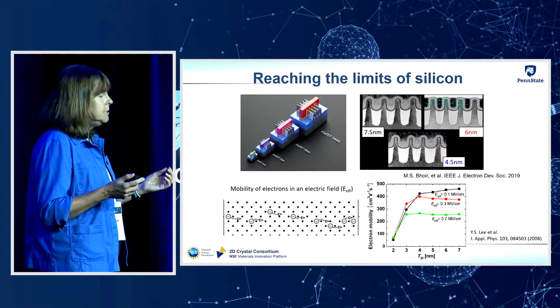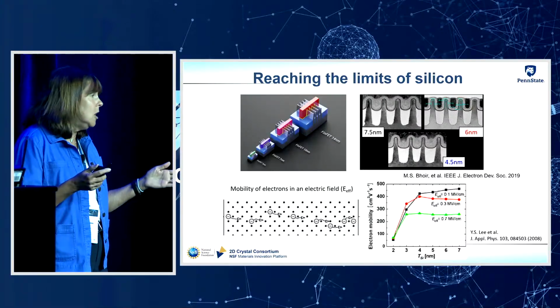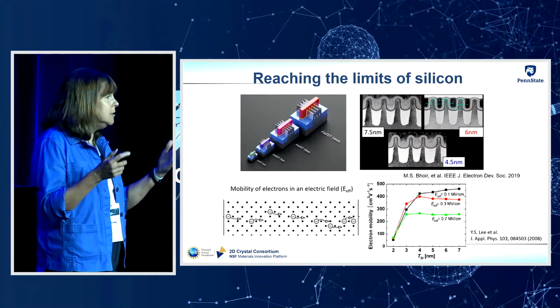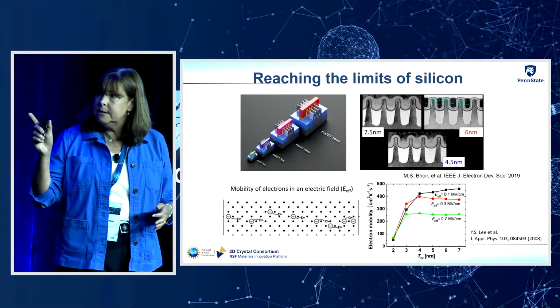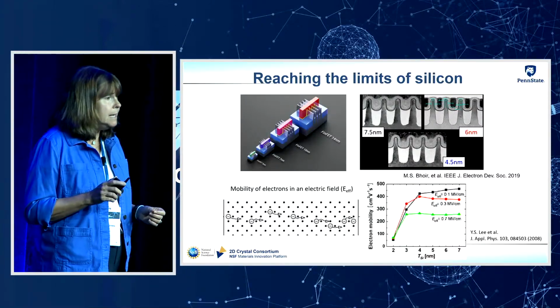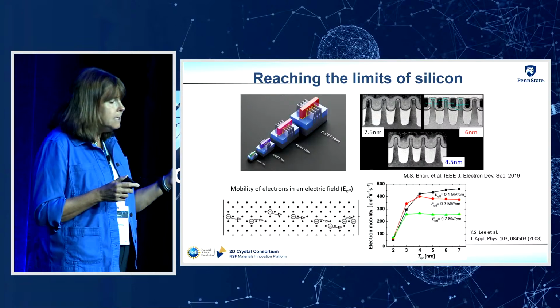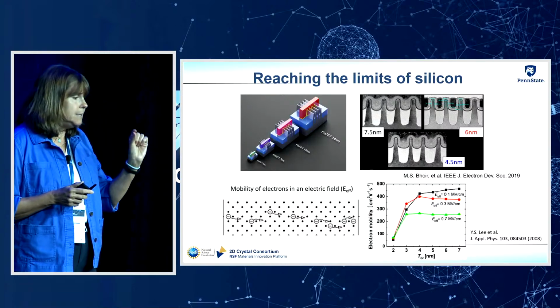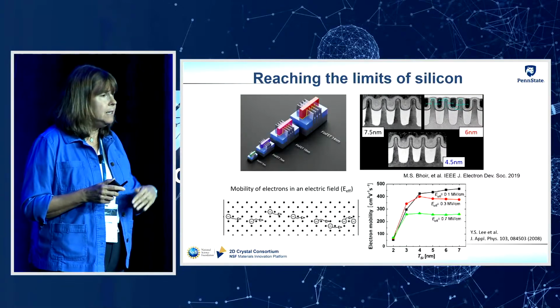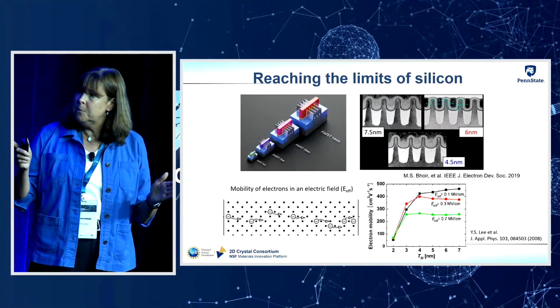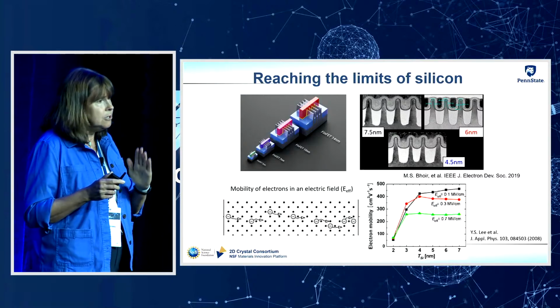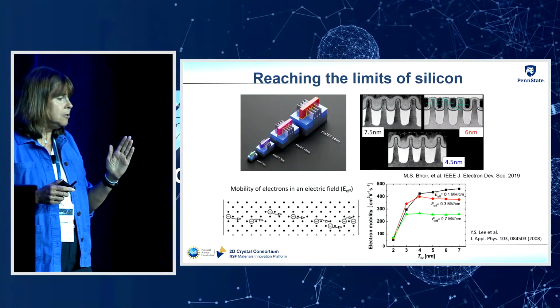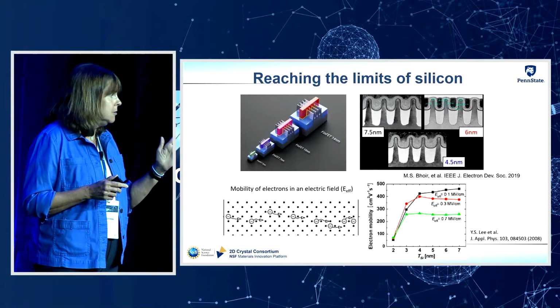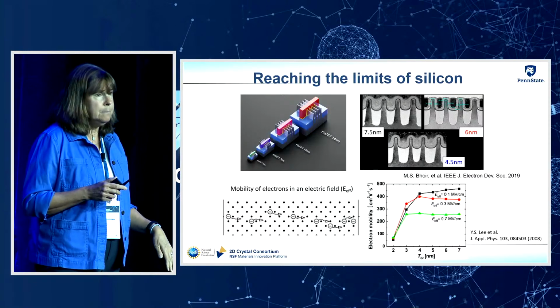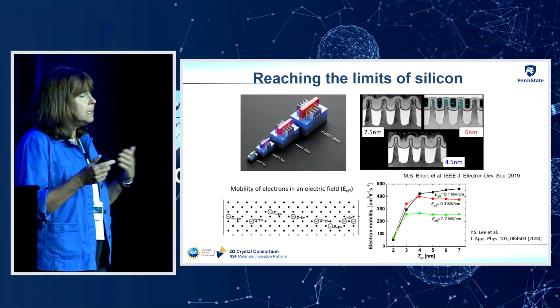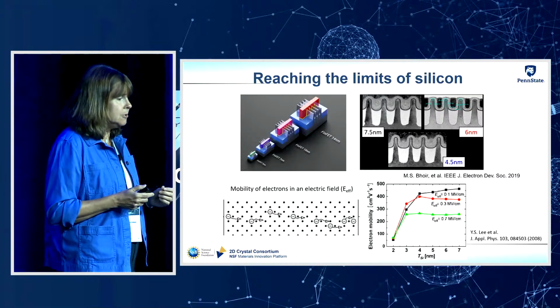So for example, if we consider the electron mobility, so that's the velocity of electrons in the silicon lattice under an applied electric field. If you take a look at the figure that I have on the lower right, this shows how the electron mobility of silicon changes as you shrink down the thickness of silicon. And it's as a function of the electric field. So you can see that the electron mobility doesn't change very much at 7 nanometers, 5 nanometers, even 4 nanometers. But once you get down below 3 nanometers, the electron mobility starts to drop off quite a bit. And that's just because you start having scattering of carriers that degrades the electron mobility.